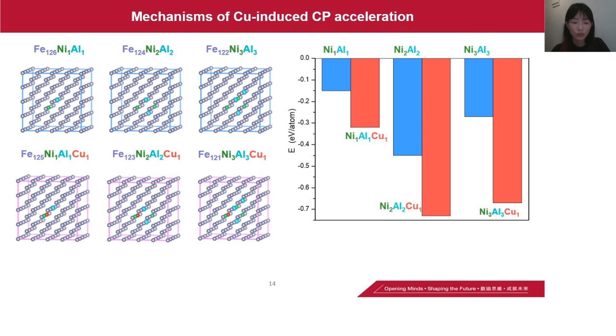Well, the results show that the formation energy of nickel-aluminum pairs in the copper-containing supercells is lower than that of nickel-aluminum pairs in copper-free supercells. This suggests that copper enhances the interaction between nickel and aluminum pairs, and thereby increases the chemical driving force for nickel-aluminum precipitation.